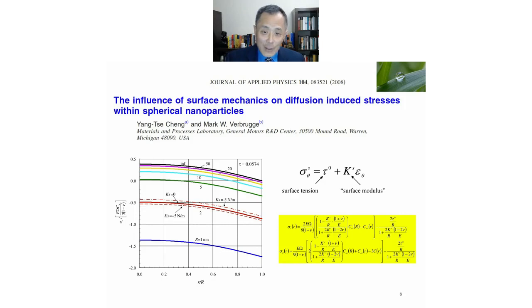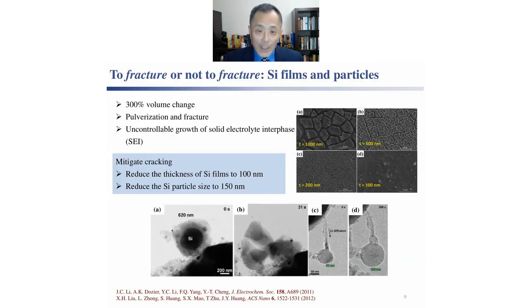That is because surface stress can exert an overall compressive stress inside the particle, and particles are less likely to crack under compression. And this effect is stronger as we decrease the particle size down to the nanometer length scale. So today we know we can avoid cracking of silicon electrodes either by having a very thin electrode or by incorporating silicon nanoparticles in a composite electrode.